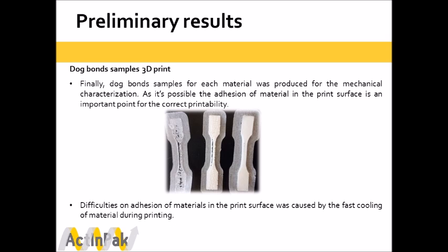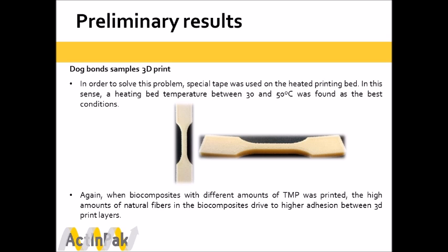Finally, dog bone samples for each material were produced for the mechanical characterization. Difficulties with adhesion of materials to the print surface were caused by the fast cooling of material during printing. In order to solve this problem, special tape was used on the heated printing bed. In this sense, a heating bed temperature between 30 and 50 degrees Celsius was found to be the best condition.